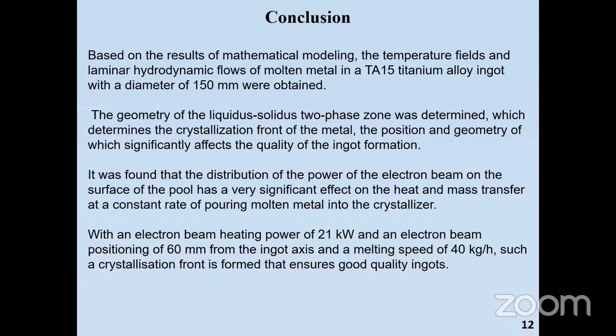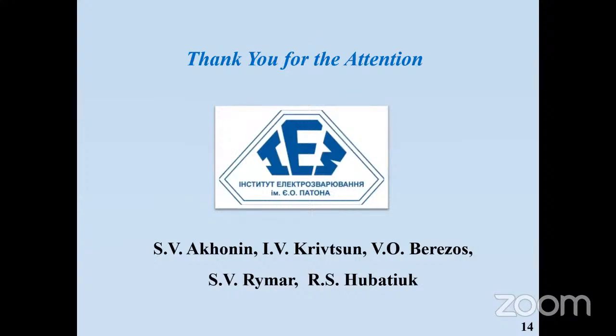It was found that the distribution of the power of the electron beam on the surface of the pool has a very significant effect on the heat and mass transfer at a constant rate of pouring molten metal into the crystallizer. With an electron beam heating power of 21 kilowatts, an electron beam position of 60 millimeters from the ingot axis, and a melting speed of 40 kilograms per hour, such a crystallization front is formed that ensures good quality ingots. That's all. Thank you for your attention.